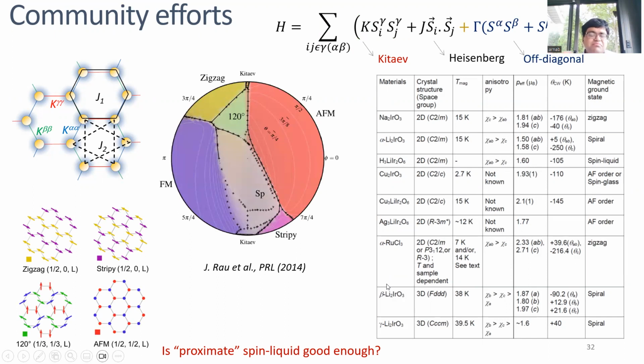But as you see, basically none of these materials are really spin liquids. And the reason is that all of them form some kind of long range order. As you see from the magnetization and the ordering temperature, all of them order; none of them form spin liquids, they form an ordered state. And the reason for that is because you get these other interactions, other terms in the Hamiltonian, such as the Heisenberg term and the off-diagonal term, which are all symmetry allowed, which means that you cannot really remove them. Which means the question is, is it true that there is really no true native quantum spin liquid in a zero magnetic field, or is there one?